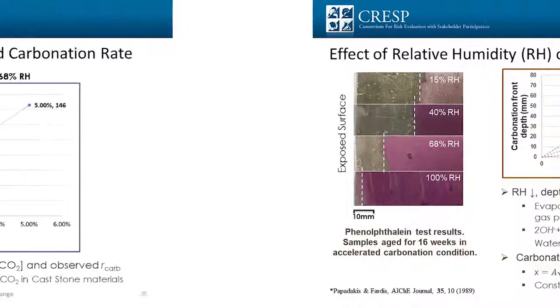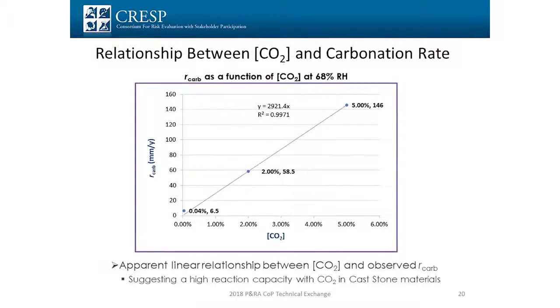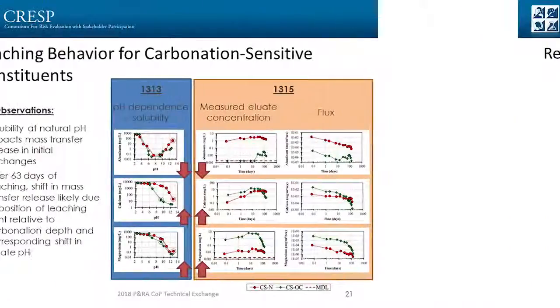And then also looking at the effect of how much carbon dioxide you have in the test chamber that you're curing it with on the rate of carbonation, and you can see this apparent linear. This is one I actually said she probably made up, I guess this means she didn't make it up, but the rest of the other ones fall right on the line. Those data are almost hard to believe. So you see this apparent linear relationship between the carbon dioxide level and the rate of carbonation.